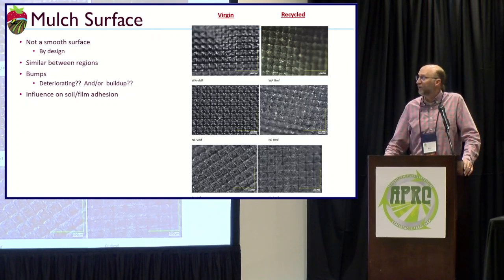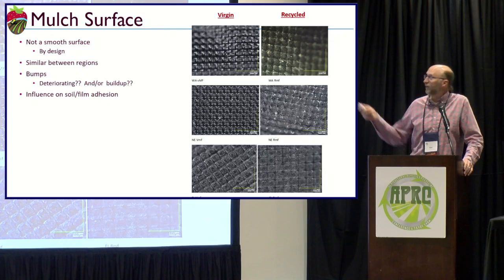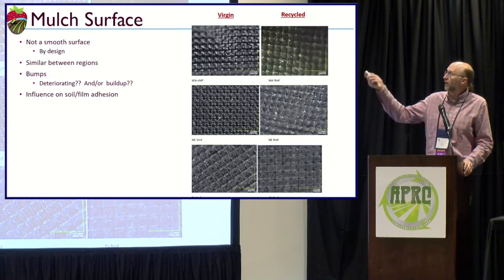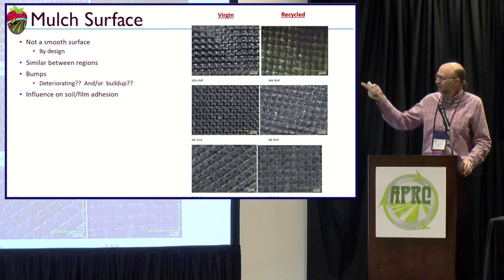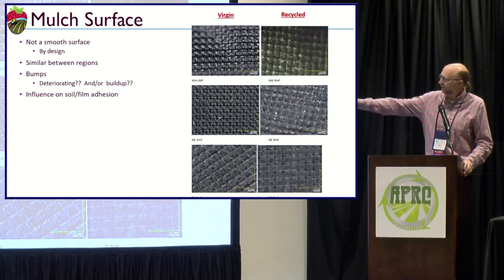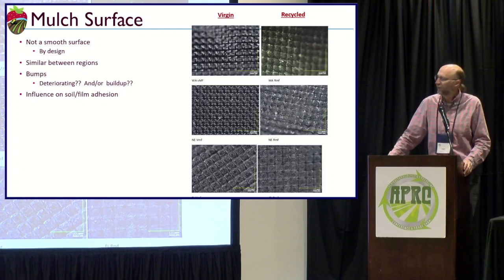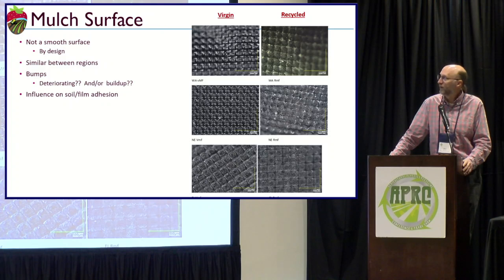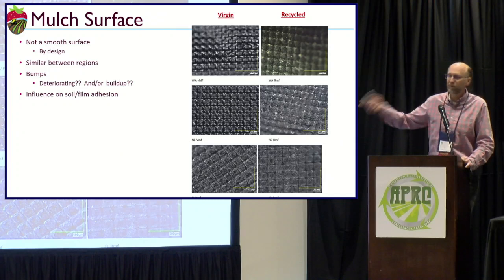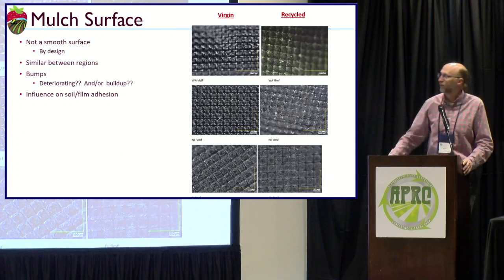So we have a virgin on the one side here and then a recycled on the other side, and you can see that they're still intact. You can definitely see that you still have the bumps, or the asperities. The question is, is it deteriorating with UV, or is that just still buildup? That's one of the things we need to figure out. But this is the washed film, the recycled film we got, and then it's the virgin film that we looked at there.